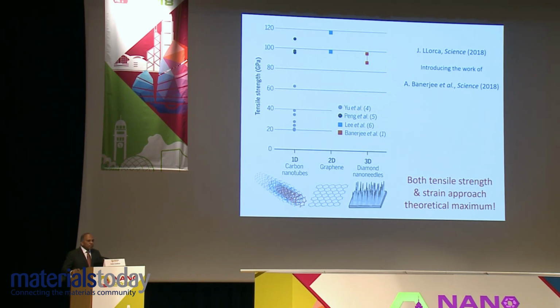delivery applications. Because diamond is also an electronic material, there is a significant opportunity to change band gap as long as you can induce elastic strains through so-called elastic strain engineering. Professor Ju Li at MIT and Professor Ting Zhu at Georgia Tech have been working on the concept of elastic strain engineering from different points of view. So rather than chemically changing the material to change the electronic as well as optoelectronic properties of diamond, there is an opportunity here to mechanically induce strains without changes to chemistry, whereby you may be able to achieve a similar effect.